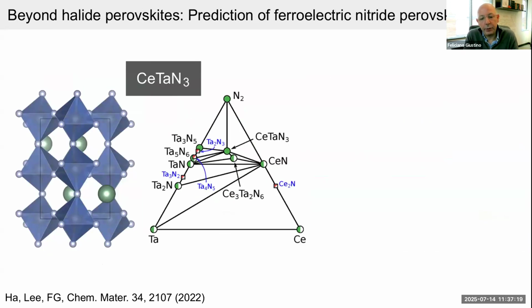Let me also mention maybe something more recent where we kept searching for perovskites that could be of interest for optoelectronics. And instead of staying with halide perovskites, we tried to look for different anions. In particular, we went to nitrides because there are barely a handful of nitride perovskites reported ever in the experimental literature. So we did a lot of work to try to look at the decomposition pathways of some of these nitrides. And we found that the cerium tantalum nitride was basically a possible candidate for a new nitride-based perovskite that would also be a good semiconductor because the band gap is of the order of 1 electron volt. And the other thing is that these semiconductors appear to exhibit some incipient ferroelectricity that comes out from the calculations.